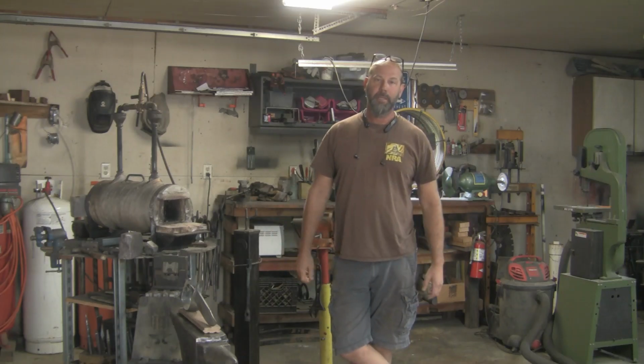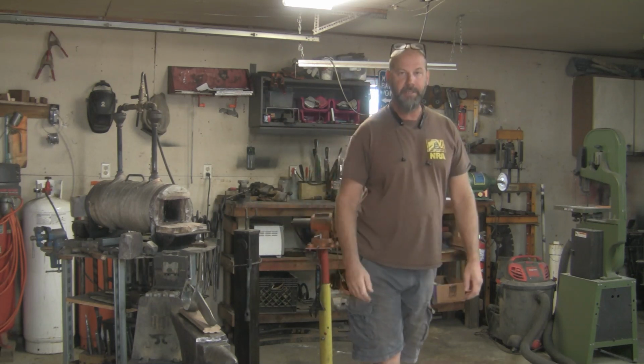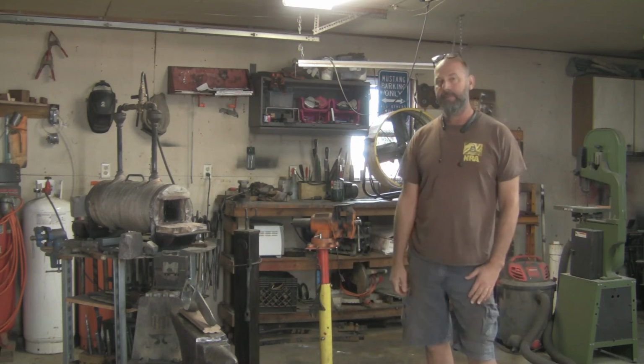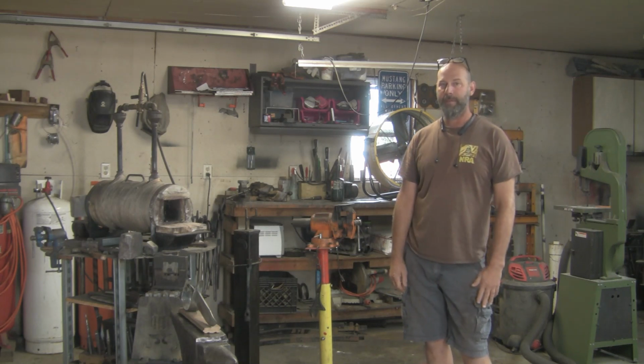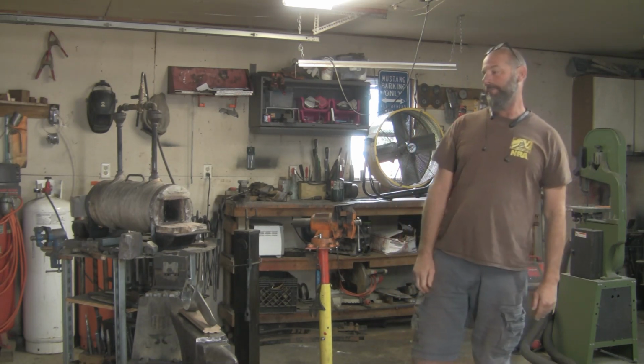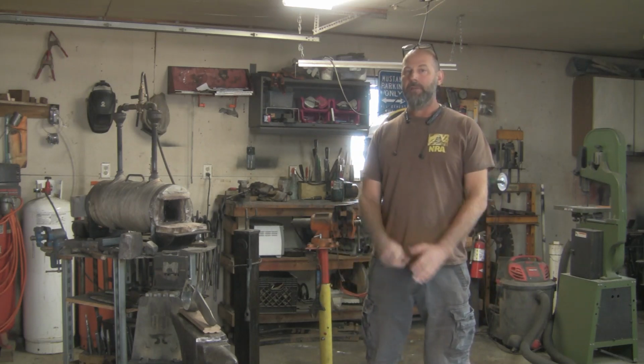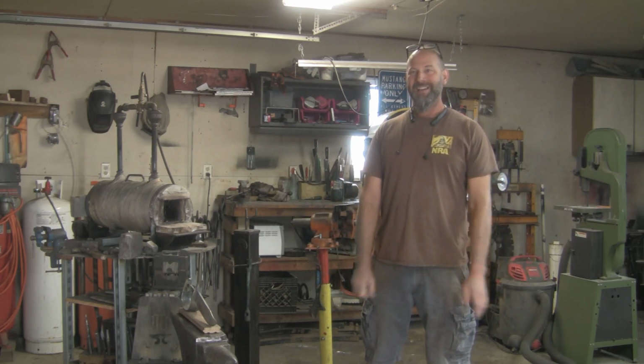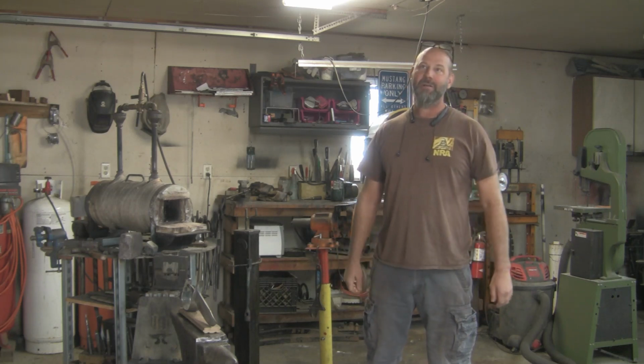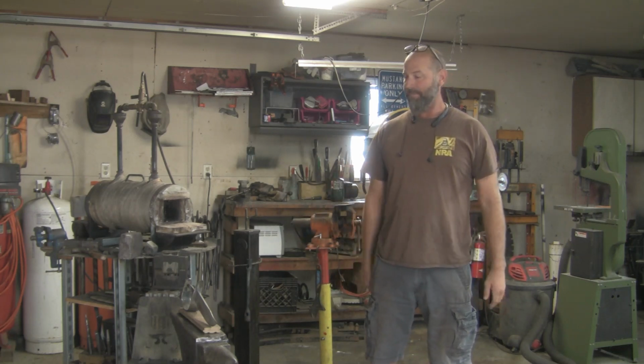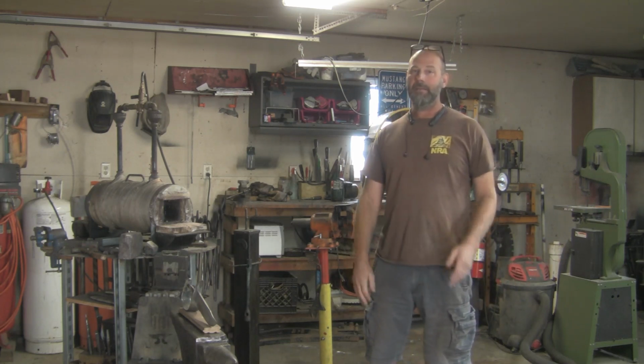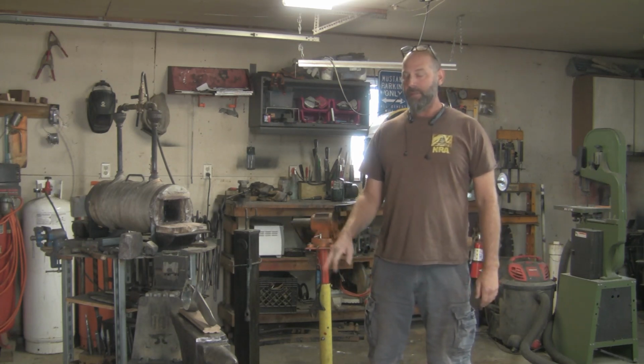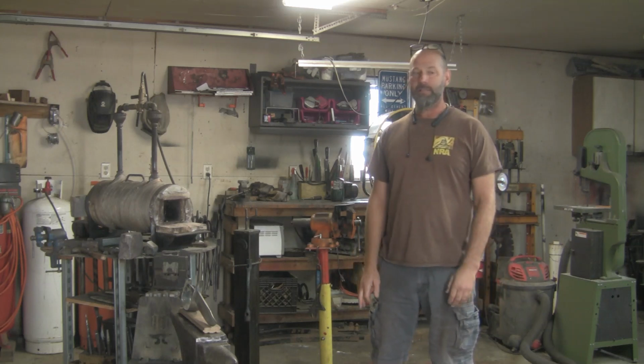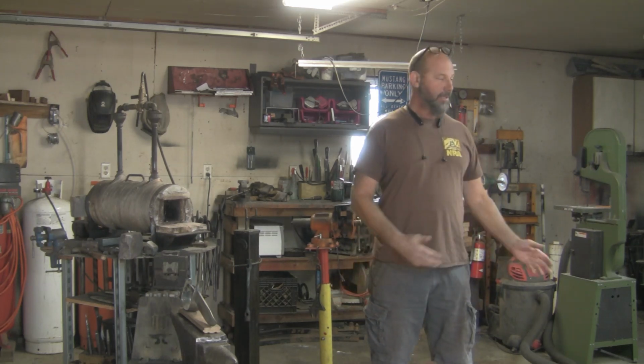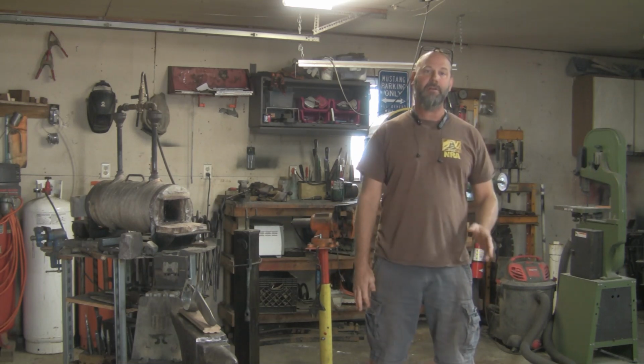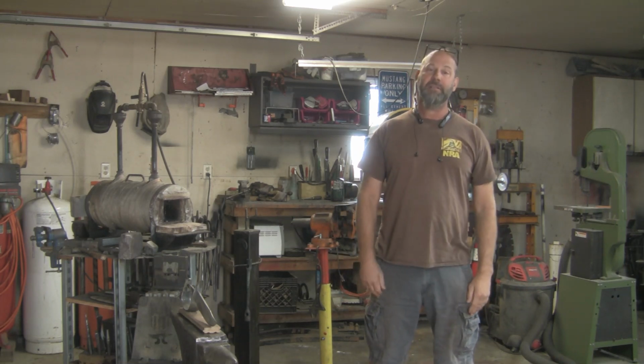All right, so it's 2 weekends later, and in the last scene we were off to temper. I did temper the knife at 375 degrees for about 4 hours. And because of the way the heat treat went, I really wasn't 100% sure what I had, so I went ahead and cleaned it up on the wire wheel and just kind of cleaned up whatever residual clay was left, any oxidations, and I did a quick etch on it just to see if there was any kind of differential hardening. Preliminary signs on that were pretty good.